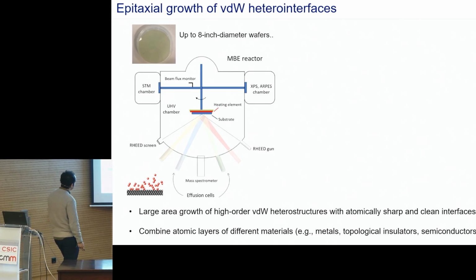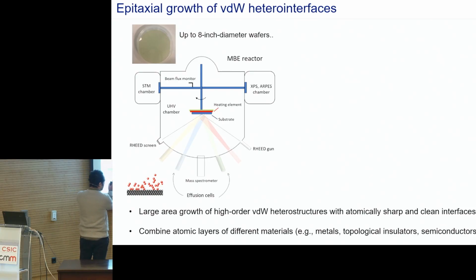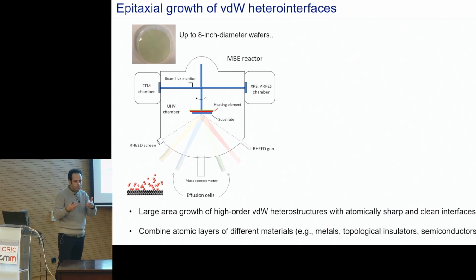So we grow these materials in an ultra high vacuum molecular beam reactor. We can grow materials up to 8-inch diameter wafers. This reactor consists of several e-beam evaporators and effusion cells where we can load our materials. So we can grow these materials layer by layer, with very good control of the thickness. And the interesting thing is that we also have two separate chambers where we can do the in situ structural and chemical characterization of the material.